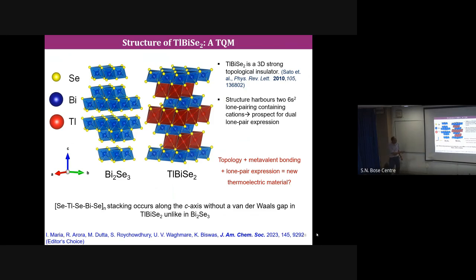So I have this bismuth selenide layer, then thallium selenide layer, then bismuth selenide, thallium selenide, bismuth selenide, and it goes like that. Thallium and selenium form an octahedra, and bismuth and selenium also form an octahedra. Both are electron deficient, because bismuth and thallium do not have the octet configuration to form this octahedra. So both are electron deficient. So let's see what happened to this material.